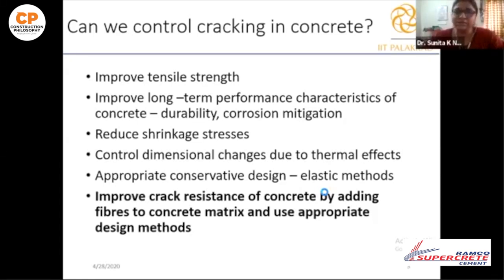The other strategy would be to reduce the stresses themselves, such as reducing shrinkage stress, using shrinkage reducing admixtures, or controlling dimensional changes due to thermal effects. This is something like neutralizing the curling completely, or reducing the temperature difference in the concrete, reducing the stresses due to temperature difference in concrete. So many strategies can be adopted from the material point of view.